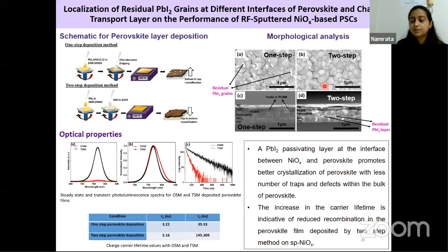When we looked at the SEM images, we saw a clear and stark difference in the top view as well as the cross section of the perovskite films. So in figure A, we can see that in addition to the perovskite grains, there are some white grains, which we assign to the residual PbI2 grains. Whereas for two-step, the morphology is quite uniform and we only see the perovskite grains.